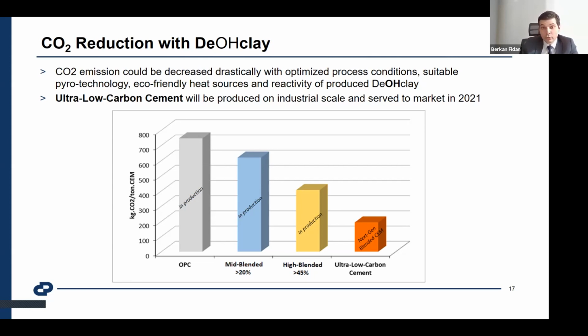The main contribution is the effect of calcined clay, because the in-process CO2 is zero with calcined clay, as it doesn't include any carbonate component. On the fuel side, we also completed the research studies. Now we are planning to implement it next month. We also minimize the combustion CO2 emissions, and by that way we could get a nearly net zero cementitious material. Adding that helped us to create ultra low carbon cement.